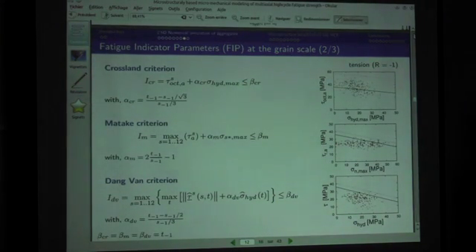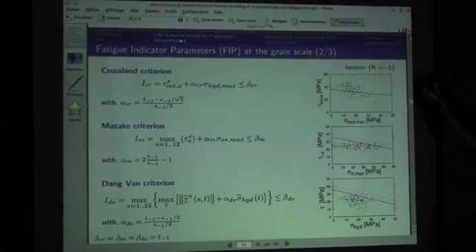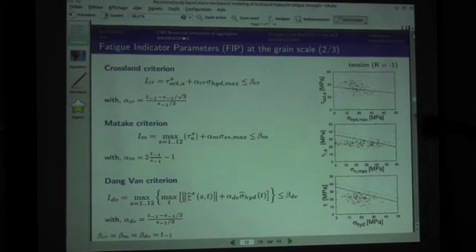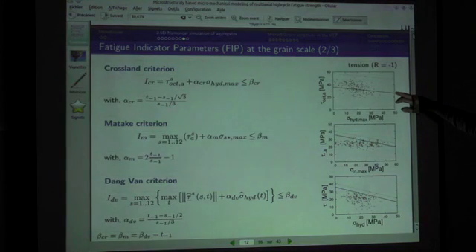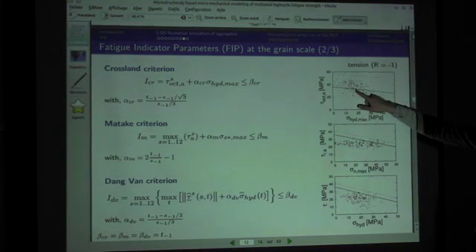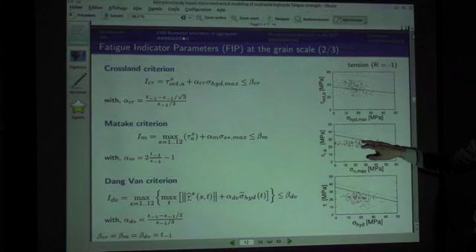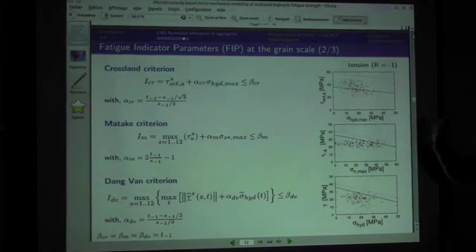So, if you do this for a different criterion, for example, Crossland, Matake, or another criterion, you can plot the macroscopic threshold of the criterion. You can plot the point that is related to the macroscopic loading you applied on your aggregate. And you can also plot all the responses of the aggregate. So all the small dots are the response of each grain to a given loading. And if you do this, you can see that your macroscopic response does not describe very precisely the aggregate response.